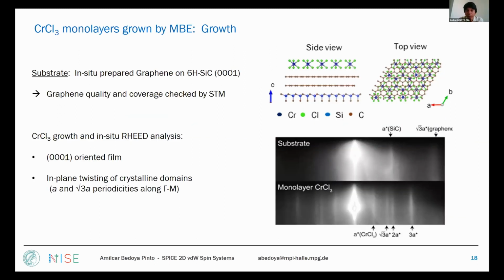So for the growth, we prepared bilayer graphene from silicon carbide. We check the quality and the coverage with STM before preparing the chromium chloride layer. And we do it in our MBE. And when you see with the RHEED pictures that you see here the substrate diffraction pattern, you will have signals from silicon carbide and graphene. And once you put one monolayer of chromium chloride, you see immediately the diffraction related to the film.